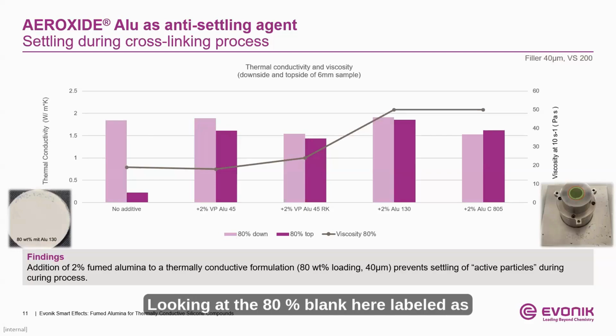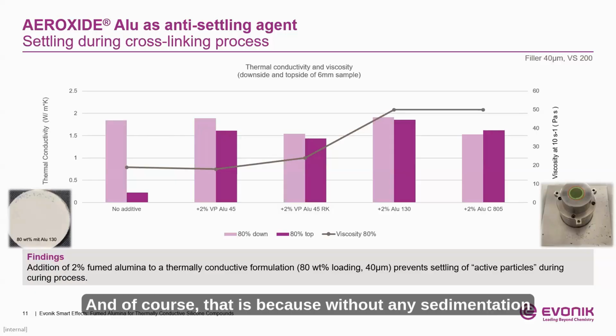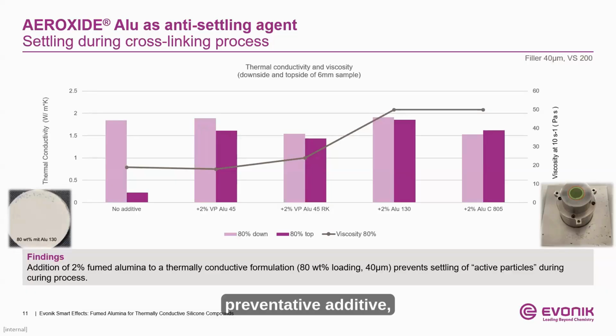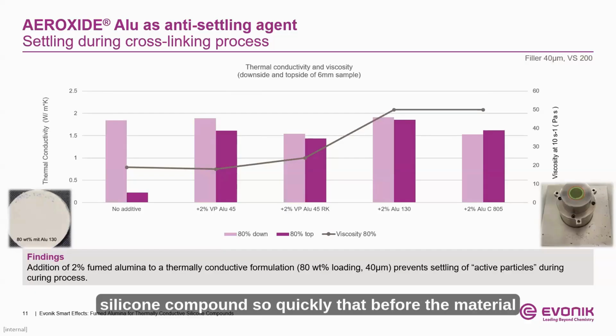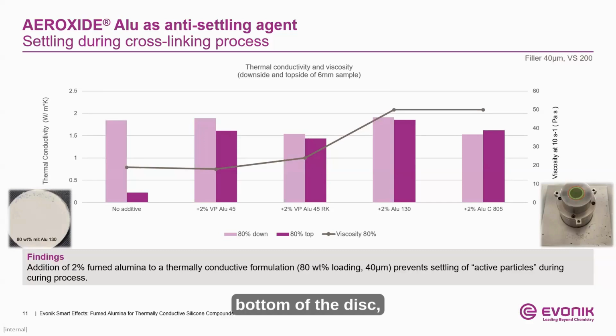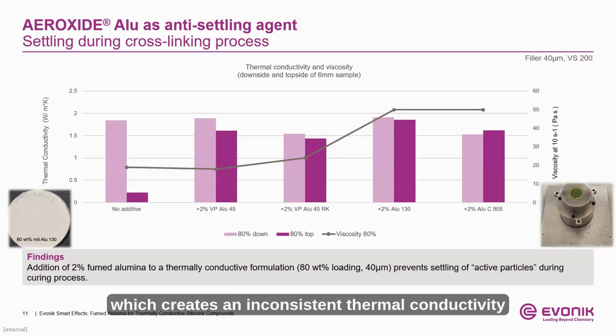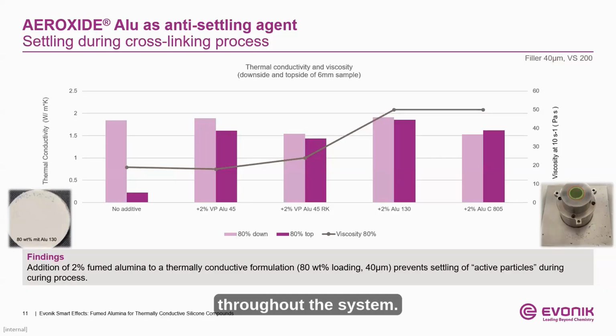Looking at the 80% blank here labeled as no additive all the way to the left, we observe a high thermal conductivity on the bottom side of the disk and a very low thermal conductivity of the top side of the disk. And you may be wondering why this is. And of course, that is because without any sedimentation preventative additive, the spherical alumina settles out of the silicone compound so quickly that before the material is actually entirely cured, the spherical alumina has essentially all settled to the bottom of the disk, which creates an inconsistent thermal conductivity throughout the system.